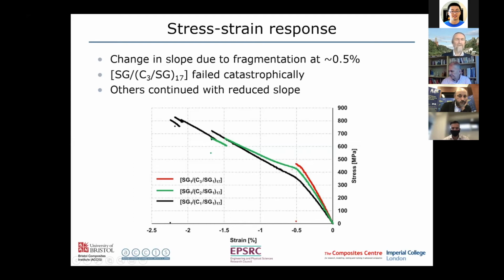So this behavior is similar to what we saw in tension, but in tension we saw a plateau, whereas in compression we still see a secondary slope here. That's because the carbon is still carrying load and can still continue to contribute much more than it can in tension, when we have these fragmentations and unloading of the carbon plies.